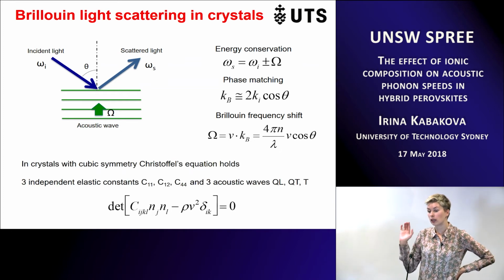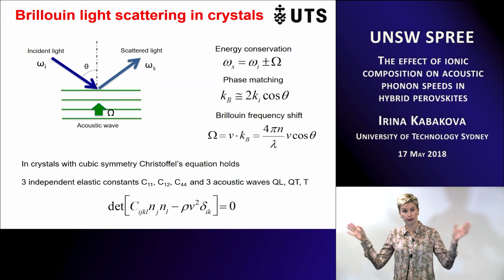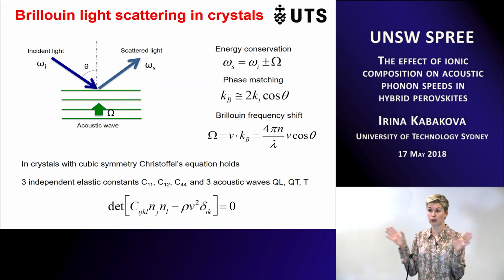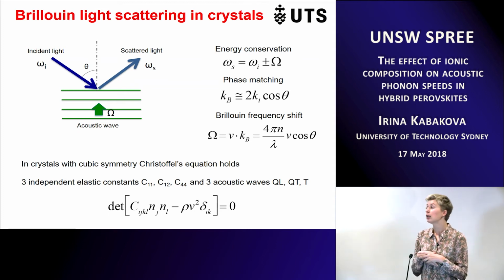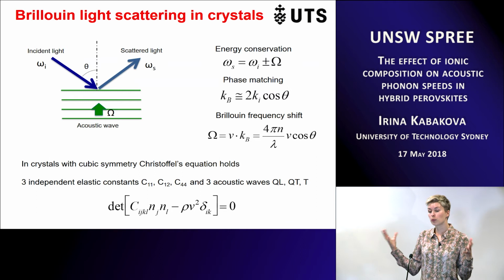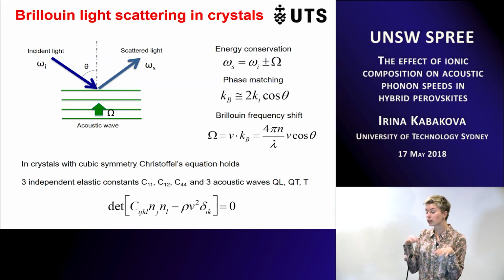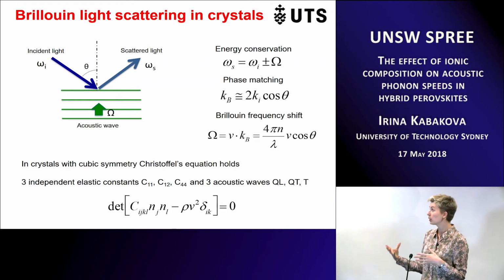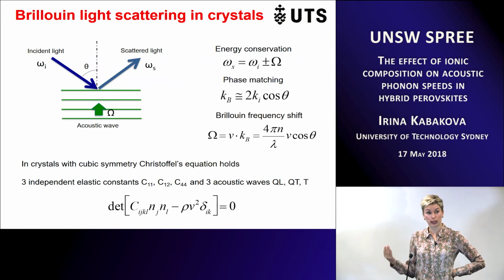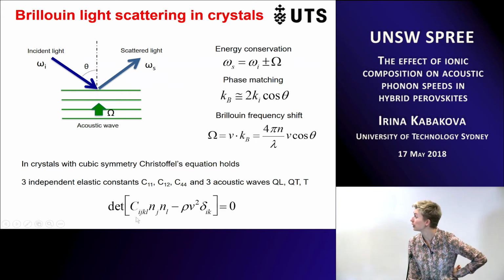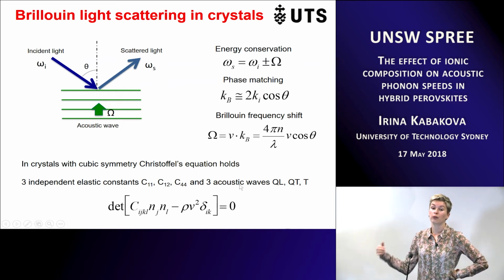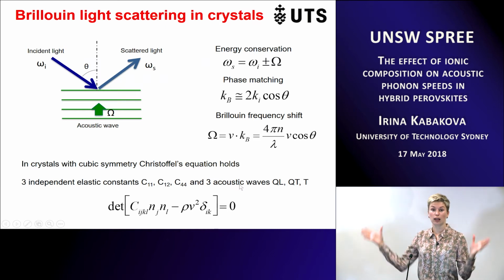And the crystals that I showed you before, perovskite crystals, are not isotropic, they actually have cubic symmetry. In materials with cubic symmetry, we have 3 different acoustic waves, and these are quasi-longitudinal, quasi-transverse, and pure transverse. So we would have 3 acoustic speeds, and we have 3 different elastic constants, and it's all governed by Christoffel's equation. So finding the speeds, we can find the constants, and we can calculate the elasticity.